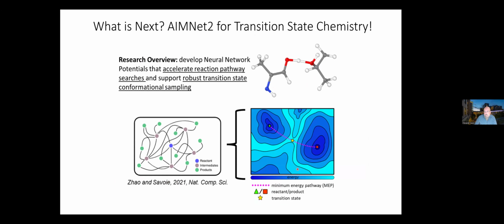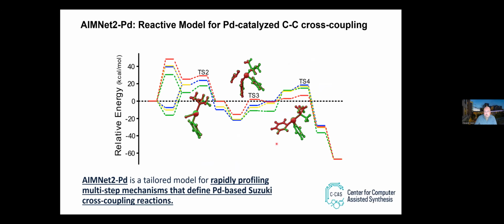So what we work on right now is to help solve one of the long-standing problems in chemistry: localizing transition states, finding the heights of the barriers of reactions, and essentially quantifying chemical reactions. One example of including the first metal element is not that we cannot describe metals, but the direction of my work is typically in organic chemistry. Palladium is the first metal we extended to, and this is very important for homogeneous catalysis, where palladium organic complexes are used in organic synthesis and pharmaceutical chemistry to do various types of cross-coupling reactions, carbon-carbon and carbon-nitrogen reactions. With that model, you can obtain geometries and energy, and do rapid profiling of the multi-step mechanism of palladium-catalyzed reactions.